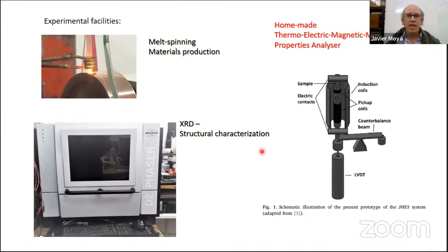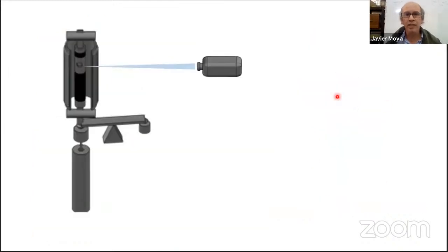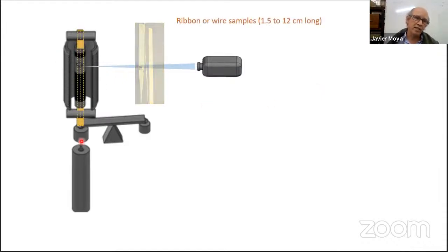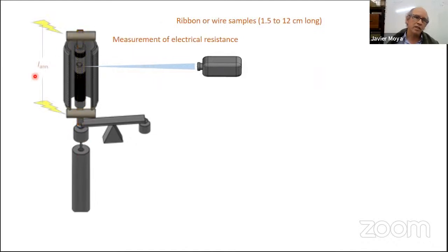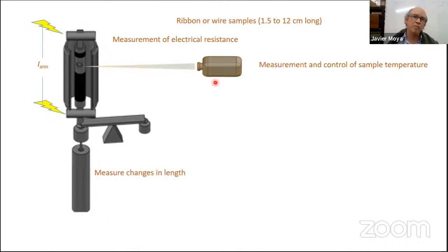Well, the most important facility we have is this homemade thermoelectric magnetic mechanical properties analyzer. I know it sounds funny that the best instrument we have is a homemade one like this, but let's see deeply. I quickly show you how this instrument works. That is very easy. We use Joule heating to heat the sample. The sample is placed inside these coils. These are the electrical contacts. Here we have a differential transformer to measure the change in length. Here we have an optical pyrometer to measure and control the sample temperature.